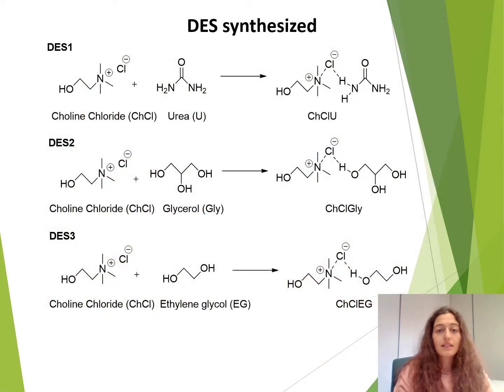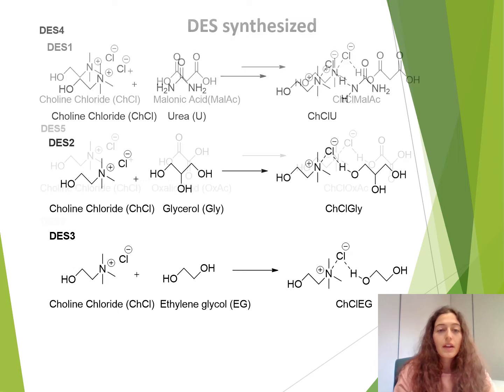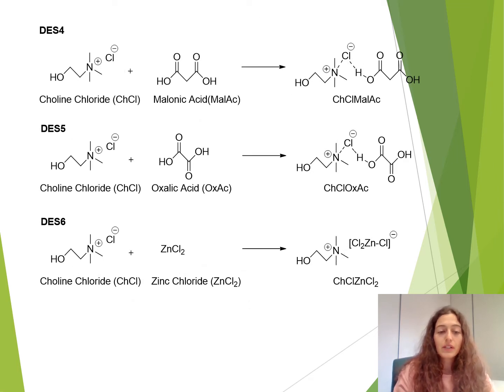I synthesized DES1 choline chloride urea, DES2 choline chloride glycerol, DES3 choline chloride ethylene glycol, DES4 choline chloride malonic acid, DES5 choline chloride oxalic acid, and finally DES6 choline chloride zinc chloride. After the reaction time, for each deep eutectic solvent a colorless liquid is obtained, ready to be used. The yield of each reaction is 100%.